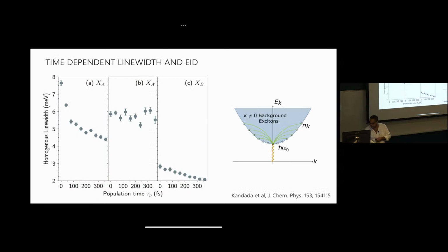But you also get information, I think, on the dynamics of the scattering if you look at, for example, the line width, the homogeneous line width. So the dephasing, the initial dephasing, this is for XA and this is for XB. You notice these start at 0 femtoseconds and they end up at 350 femtoseconds.